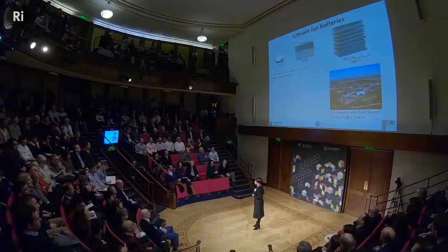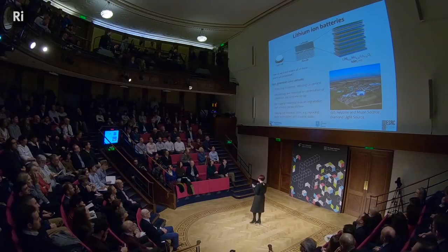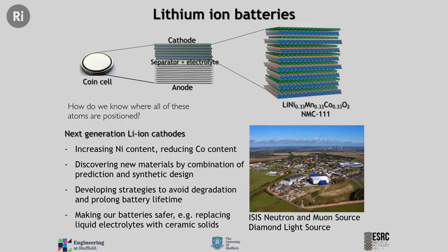So over time, lithium and nickel, I didn't show this in the image, but lithium and nickel ions are very similar in size. And you may have noticed when you buy a new device that your battery works really, really well, but a year or two later, the performance isn't as good as it used to be. And that's because over time, those electrodes start to degrade a little bit. Atoms start moving into the wrong positions, your electrode materials start to crack, you start to just get the breakdown of your material over time.